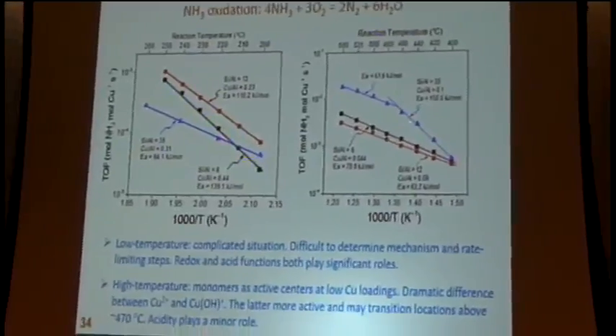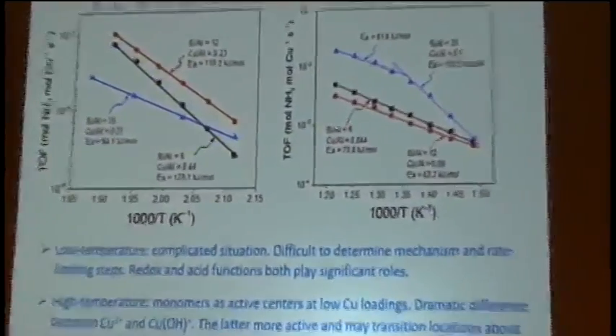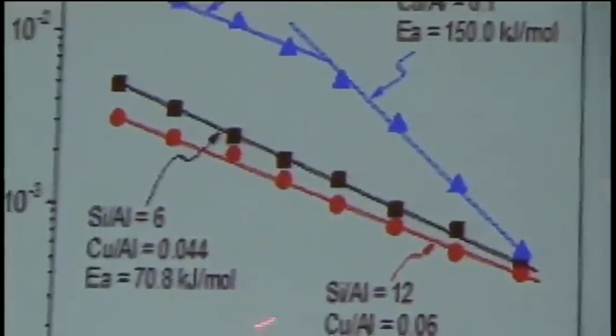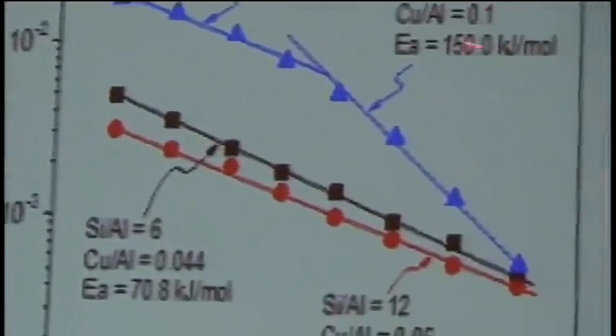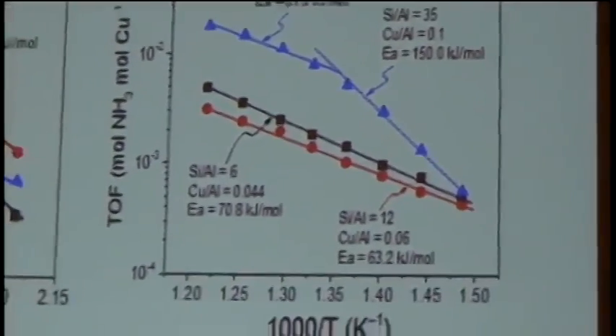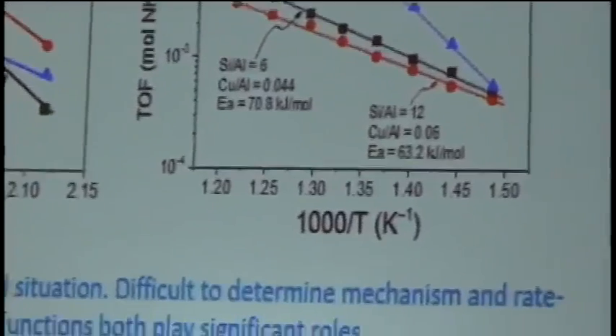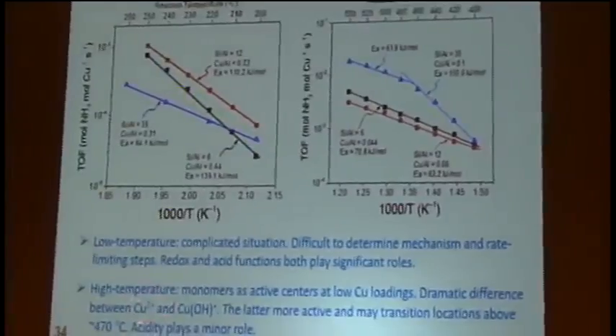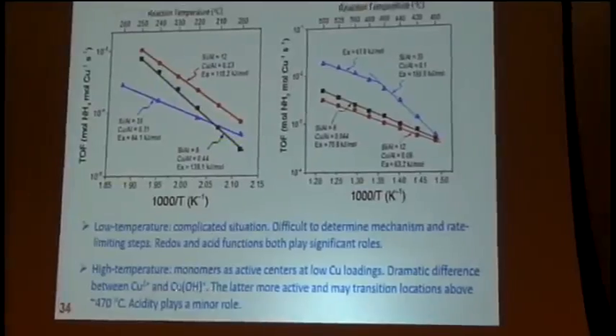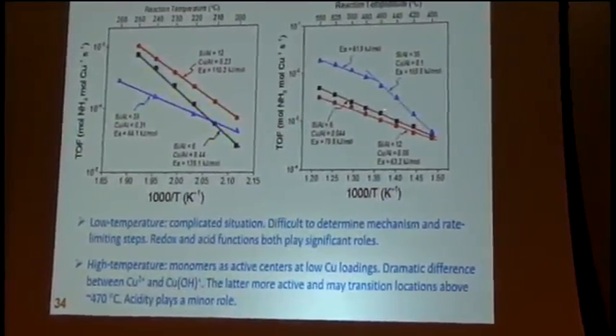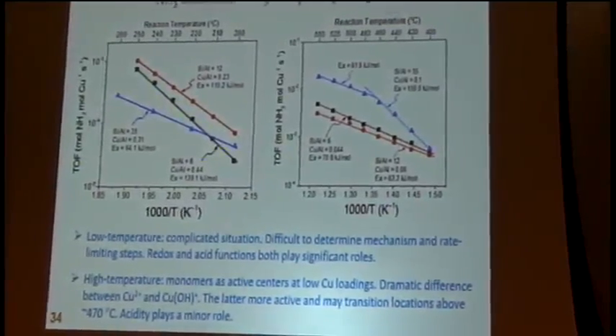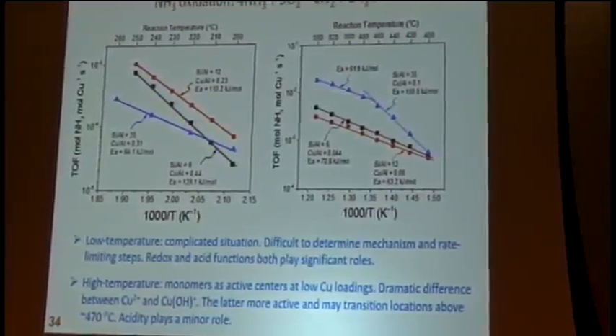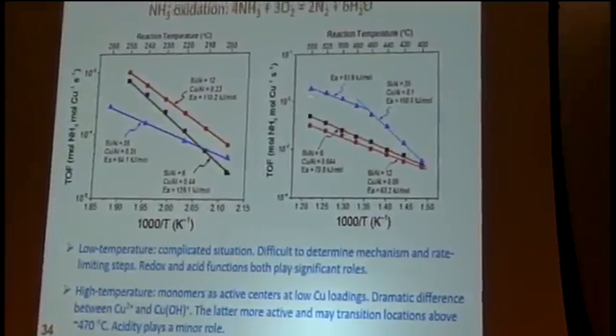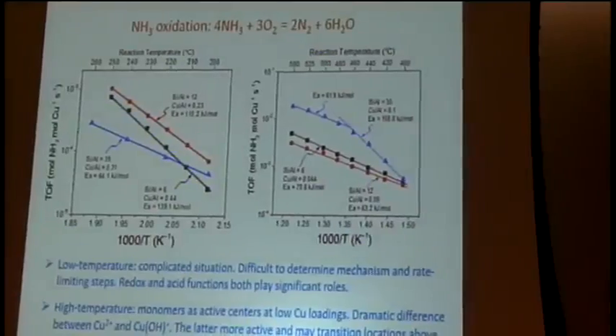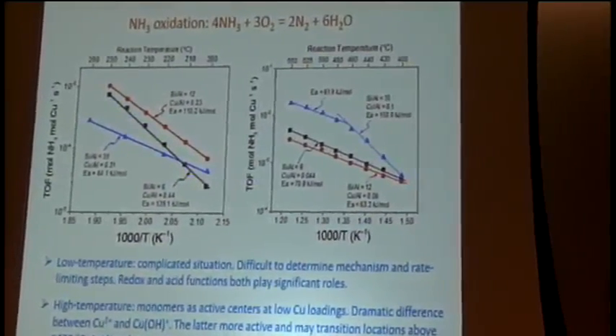In the high temperature regime, the situation is much simpler. These two samples with Si/Al ratios 6 and 12 are very similar, but apparently the activity is lower than the sample at Si/Al ratio 35. This probably means that the catalytic properties in ammonia oxidation between Cu2+ and CuOH are different. CuOH seems to be much more active compared with Cu2+ for ammonia oxidation. And there might be a transition in the population of those species as a function of temperature, because we see this transition in our Arrhenius plots at temperatures around 470 Celsius.